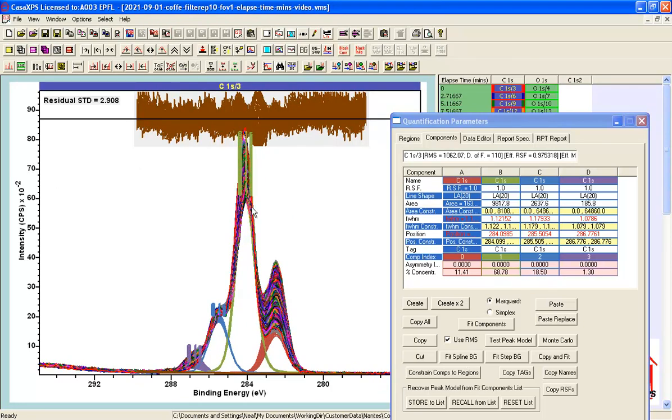So what we've done is estimate from the entire data set the full width half maxima and positions, and the success or failure of this type of operation will depend on how these data are located with respect to energy. If the energy for each spectrum is consistent with the other spectra, then we will get a result that is valid. If data shifts and there are other factors involved, then this type of operation is not appropriate. We would need to do energy calibration before applying these types of estimates for width and position.